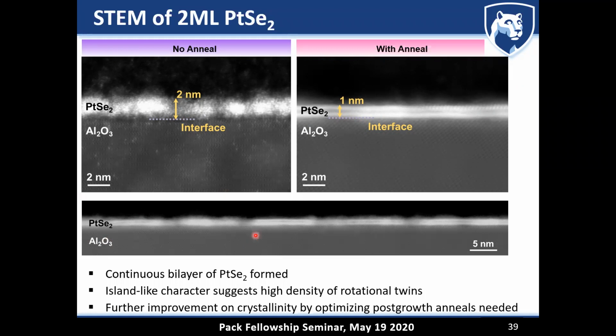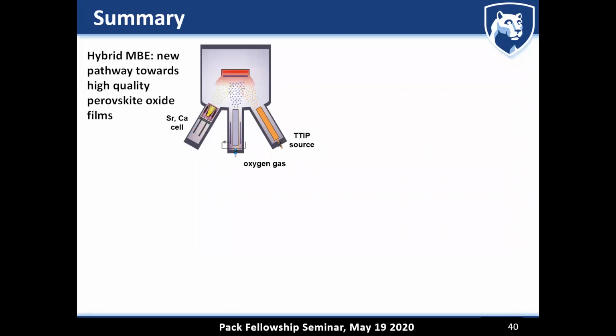However, it looks a little bit jiggity, and this is simply coming from the fact that these bilayers are not single crystalline and have the right orientation, but there's a high density of rotational twins formed, and they're just getting stitched together somehow and going to have quite a lot of rotational domain boundaries. So clearly, this is the start, and it requires further improvement, in particular on the crystallinity of these platinum diselenide films. And that just means that we have to do a better job in this post-growth selenization anneal. So this is a little bit of the overview that I wanted to just share with you.